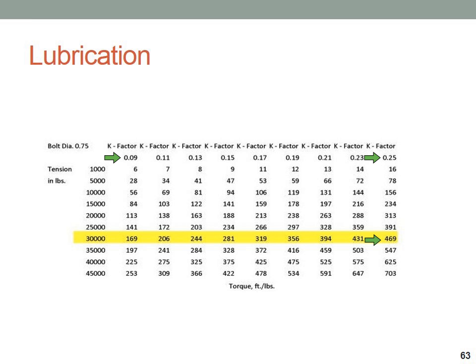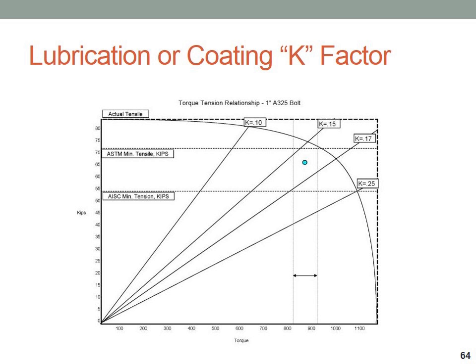Other industries that are a little farther along than ours, Japan for example, actually sell all of their structural assemblies as matched sets in different categories. One of those happens to be that the assembly has to be between a 0.15 and a 0.17 K factor. In that case, you can use torque in a pretty reliable manner because there's really not that broad of a range when that K factor is controlled. It's when we don't control it that's a problem.